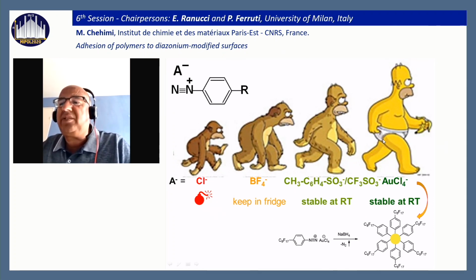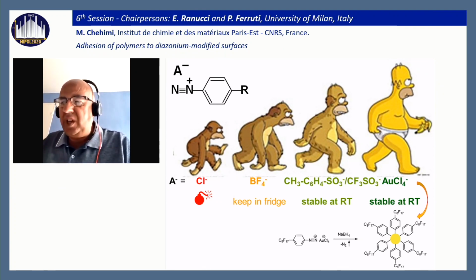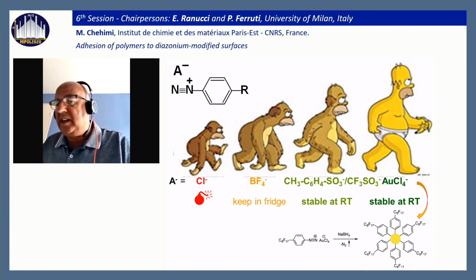And these are, for me, probably the most important ones. They are stable at room temperature, diazonium tetrachloroaurate, because when you reduce these diazonium salts, both the diazonium and the tetrachloroaurate reduce. So this is reduced to gold nanoparticles, and it is capped by aryl groups. So these are important to make, in one step, aryl-capped gold nanoparticles.